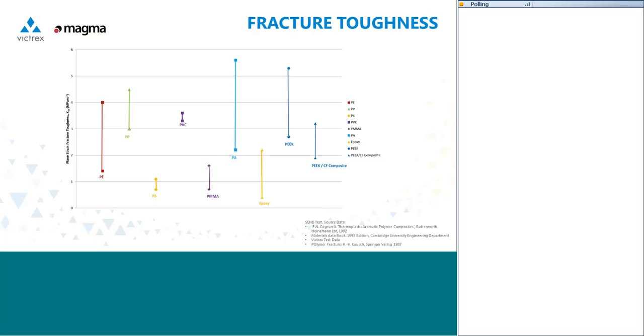This chart is something I've pulled together from searching on the internet, and it's simply to demonstrate that there is quite a range of fracture toughness as you look between different polymers. But PEEK, according to my survey of the available data, depending on the grade and so on, is right up there among the tougher of the materials. And you'll see even the PEEK carbon fiber composite has fairly high levels of toughness.